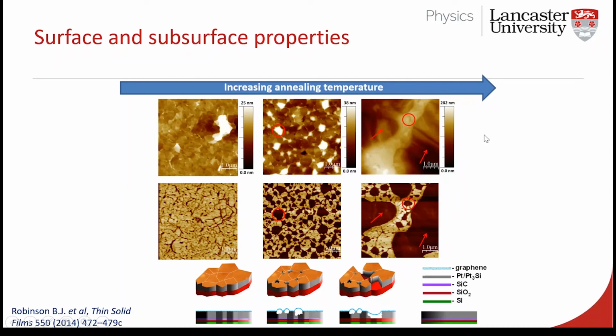So what you can interpret from this is there is a change in the underlying structure. We know the surface doesn't change because we have the chemical mapping of that. That's just carbon. It is the underlying structure that's changing. And now we're using these mechanical maps to understand that actually it is the catalytic surface underneath that is falling away, it's degrading. So you can see in my cartoon down at the bottom here, depending on annealing temperature, it's getting little holes, little fractures showing up in it. Otherwise, it's being completely degraded away. And you can see that in the mechanical maps.